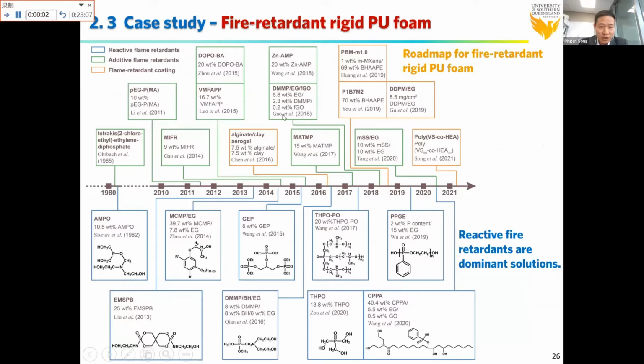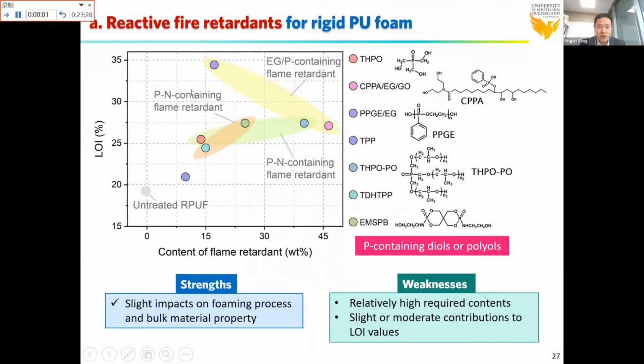So for flame retardant rigid PU foam, this picture just shows the roadmap. Basically you can look at the top: additive flame retardants and also flame retardant coating. But the reactive fire retardants are the dominant solutions. For reactive fire retardants for PU foam, they are basically phosphorus-containing diols or polyols. These reactive fire retardants only have a slight impact on the foaming process and bulk materials. It's very ideal for PU foam. But its weakness is that it requires a relatively high loading level to reach the desired V0 rating.